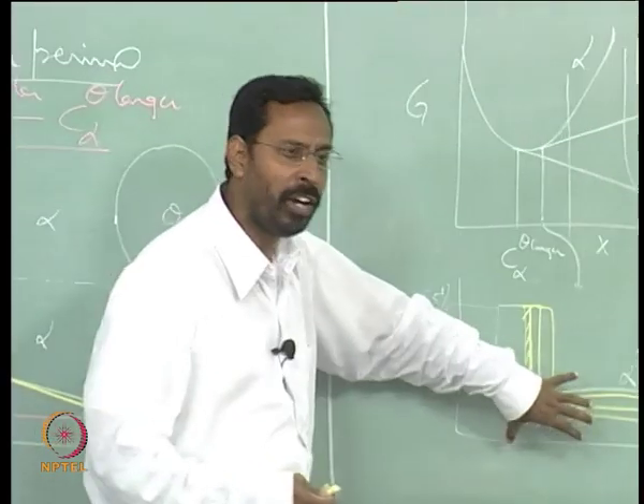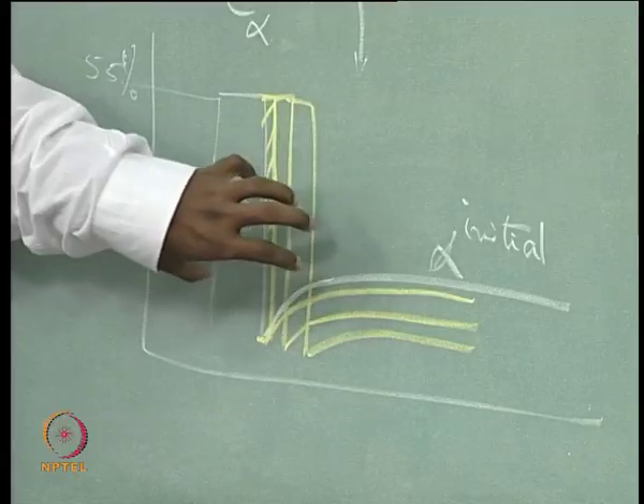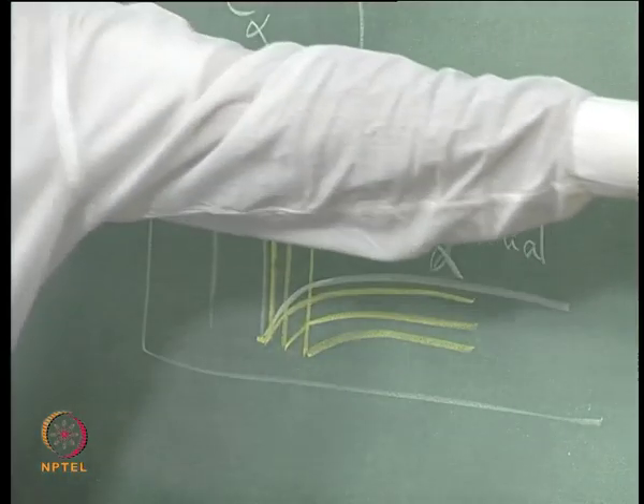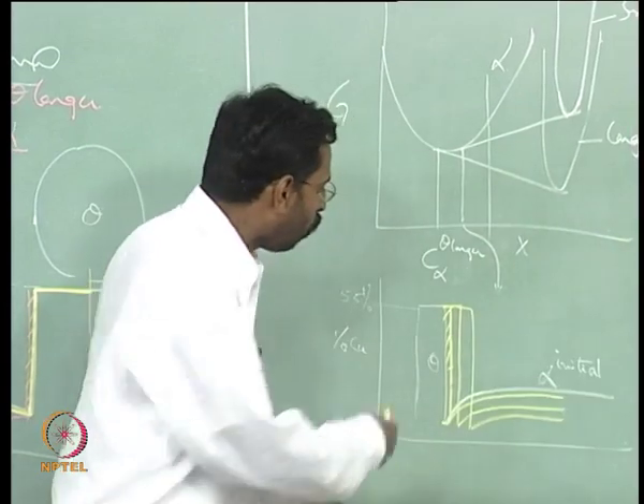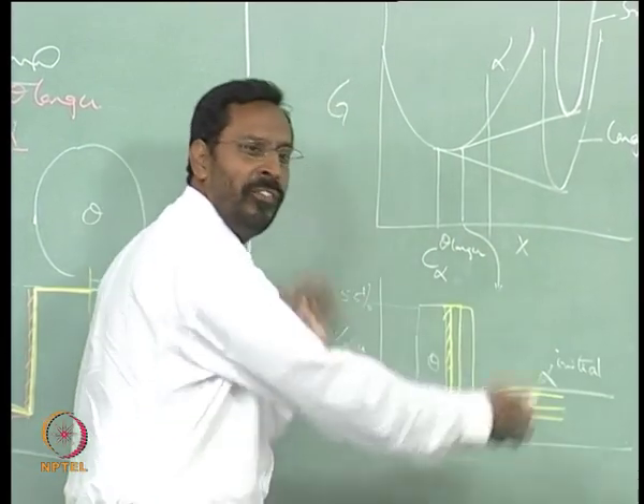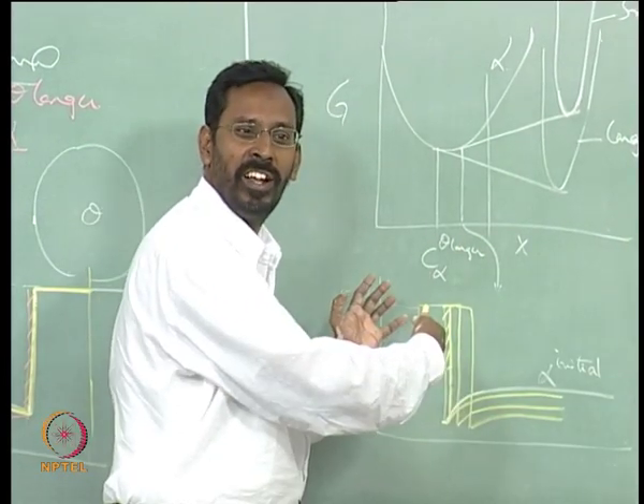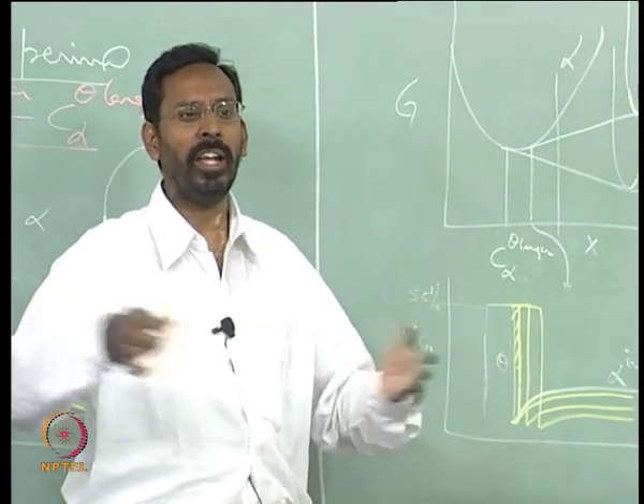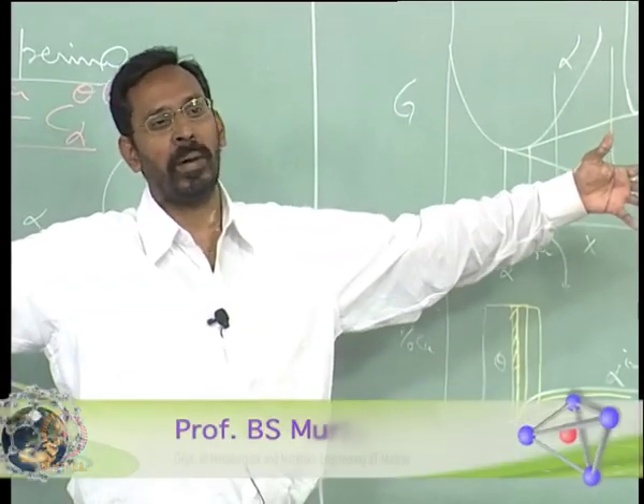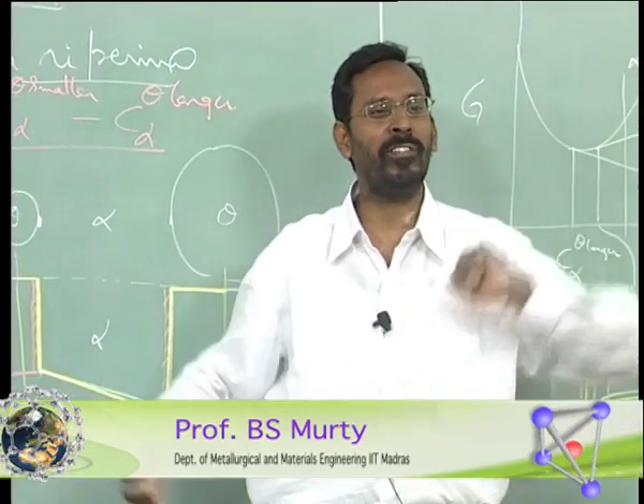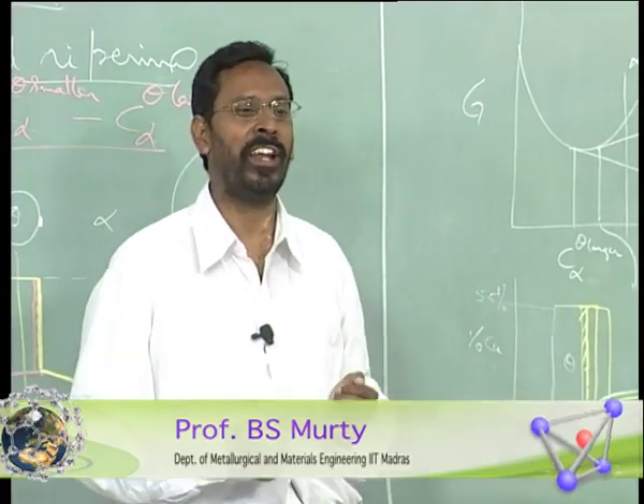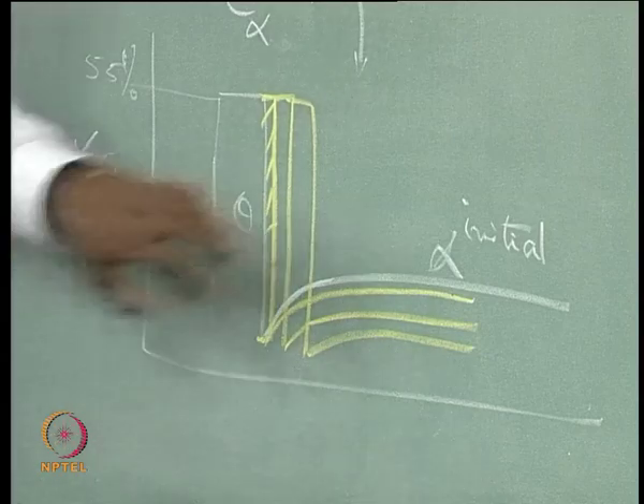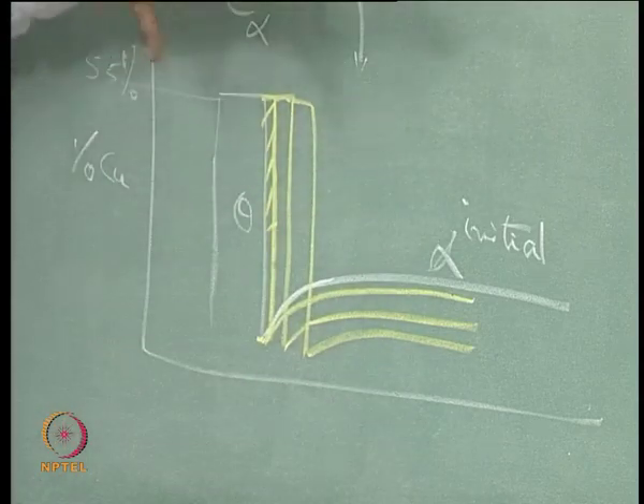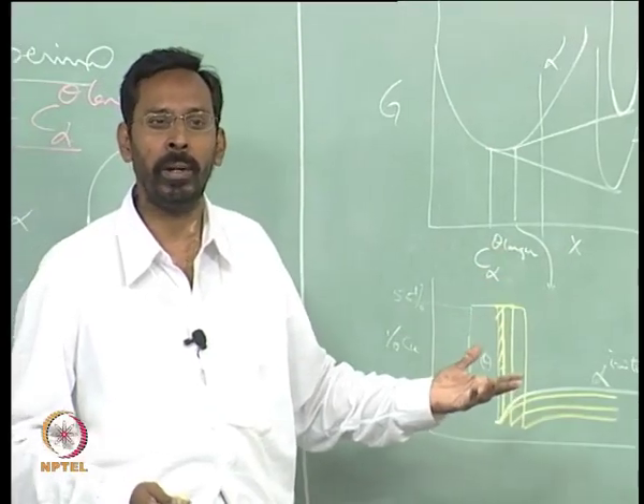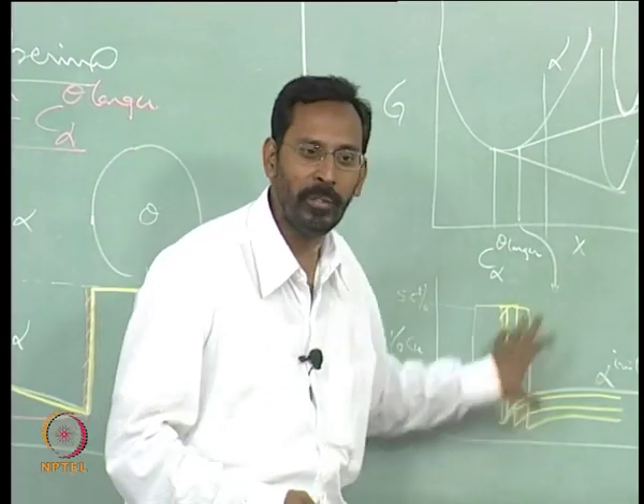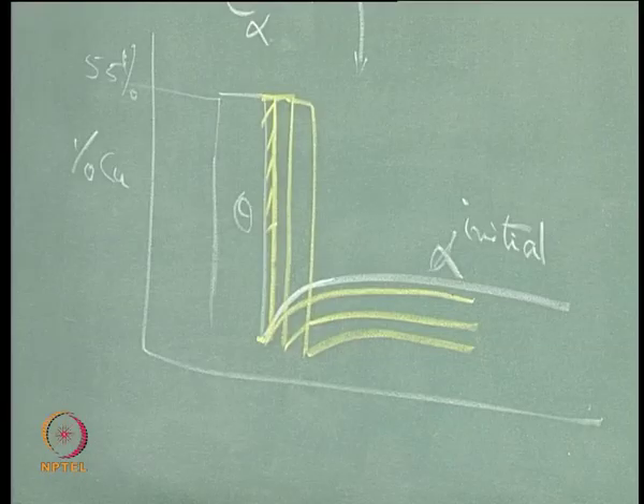No, we are talking of a small region, a very small region, okay, and there can be some other region where, see, this whole thing is happening in a region of a few 100 nanometers, and in an alloy, okay, the grain size itself is very large, 100 microns or so. So, in some other corner of the grain another nucleation event can happen. We are talking of that particular theta, because the theta in the beginning is about 10-20 nanometers, and how that particular theta is growing, that is what we are looking at.